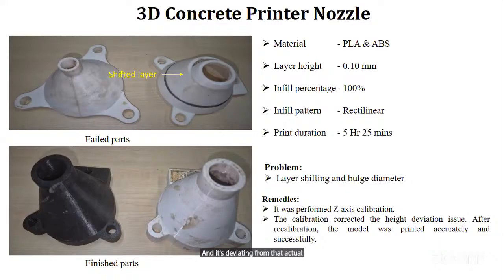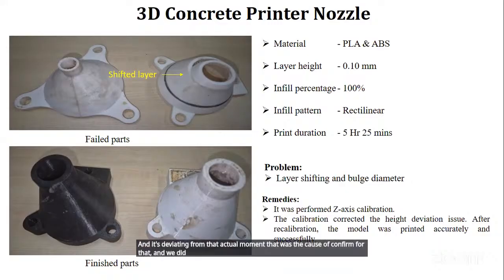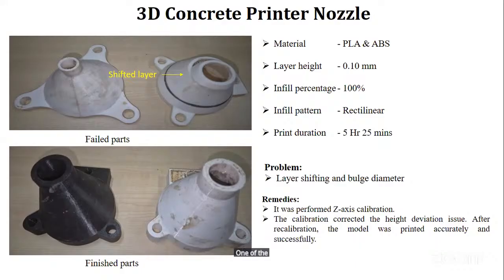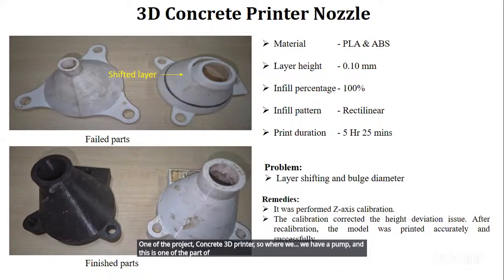That was the cause of concern, and we did the recalibration, and it was successfully printed. This printer nozzle, one thing I want to highlight here, was part of one of the projects, a concrete 3D printer, where we have a pump, and this is one of the parts of it. So we are printing for that, and this issue occurred multiple times. We printed, and finally we achieved it, and for that printer we received an award at NIT Warangal with a cash